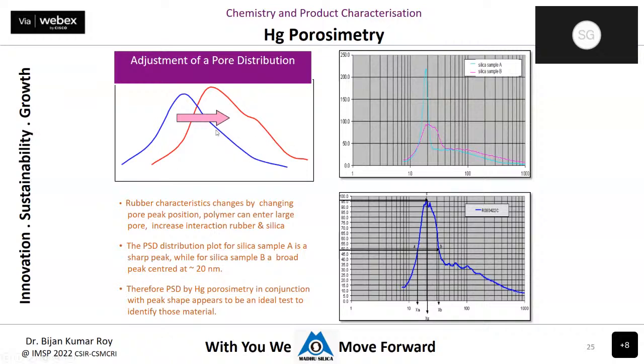Now, I'll show you this graph. This is the conventional kind of silica, where you can see the peak sharpness. This is a sharp peak. For the highly dispersible silica, the peak is broadened and extended. Since the polymer is a larger molecule, your silica should be porous, and it should have a broad pore size distribution like this. This is a single adsorption, a monomer kind of silica. But when you talk about this highly dispersible silica, we require this much broadness of porosity. So pore size distribution plays an important role, and mercury porosimetry is the instrument by which we can measure the pore size distribution, the pore size, the average pore size, and different calculations.